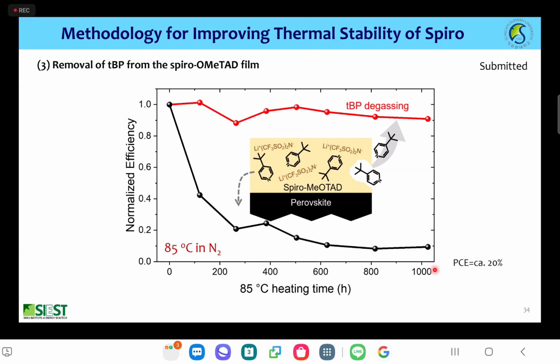But we are interested in the spiro compound because the spiro compound always delivers better efficiency than the other developed or reported hole conducting materials. Therefore, we would like to find out the origin of the thermal instability of using the perovskite. Then we found that in the spiro film there is still TBP remaining in this spiro compound film. And then we found that the TBP is the killer for this thermal stability issue.